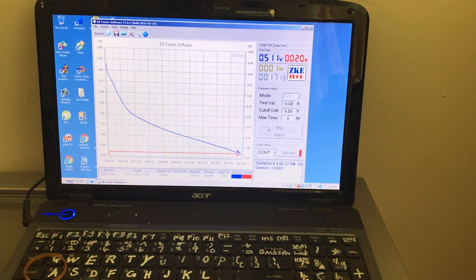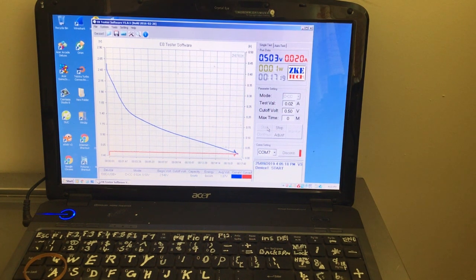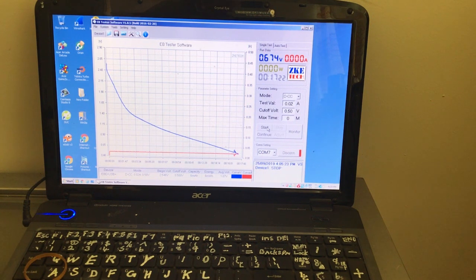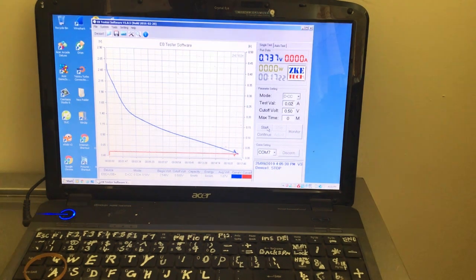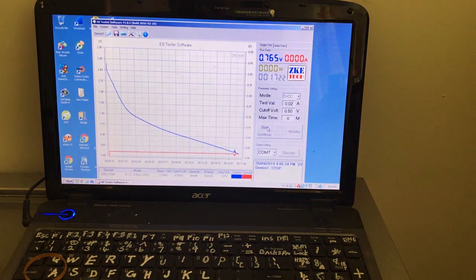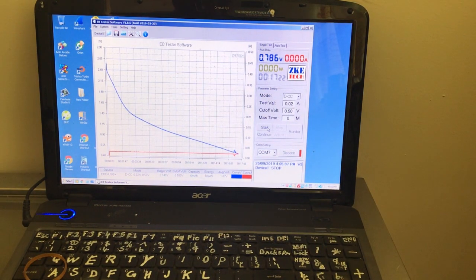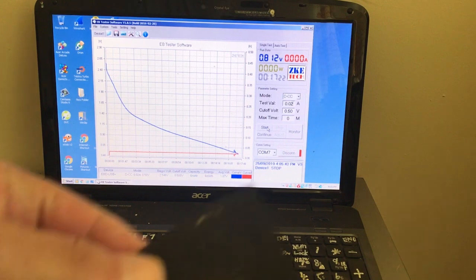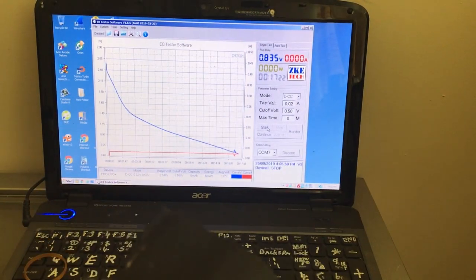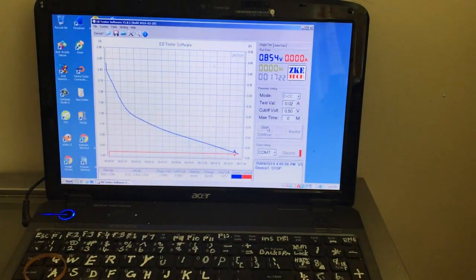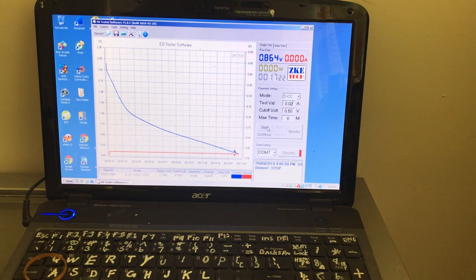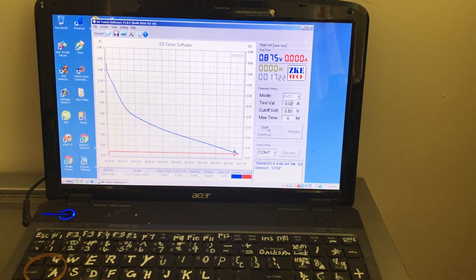Okay, I don't think we're going to get our 20 minutes. We're at 17 minutes. I'll soak them in electrolyte overnight and redo the experiment. Maybe pushing it with too much resistance with 4 sheets of the paper coated in carbon perhaps. So, we only got 6 milliamp hours and 6 milliwatt hours. So, we're down by 4 with that extra piece. It could be still dry. It's quite too much binder I'd imagine being low on resistance. It's quite flexible. It doesn't crack. But, it's too high in resistance for now. I'll work on the formula of that.